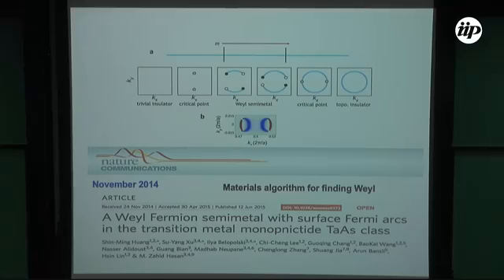Now all you do is either break time reversal by magnetically doping the system, or break inversion symmetry. In both cases, the Dirac point has to split. The degeneracy is lifted, so you'll have a pair of Weyl points, Weyl nodes, and on the surface they're connected. This is the Fermi arc.